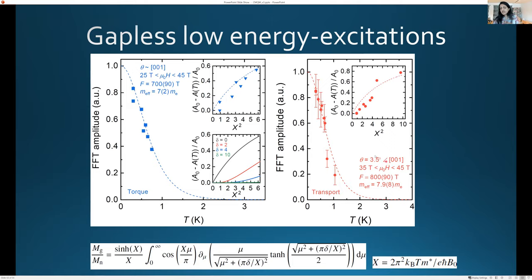And both for quantum oscillations in electrical transport, so you can see the growth at low temperatures, and the gapless simulation, and magnetic torque, you can see that there's rapid growth as you go to low temperatures, which is consistent with a gapless model and which rules out a gapped model. And for Samarium hexaboride, I didn't show this because the growth is even more strange. It's not even Lifshitz-Kosevich-like, but I could do that down to 1 Kelvin and we would see the same behavior. In this case, we can go down to about 500 millikelvin and say, okay, the gap, if anything, has to be below 500 millikelvin. Whereas in the Samarium hexaboride, we can go down to 30 millikelvin and say, it's gapless down to 30 millikelvin. So this model is ruled out as well.